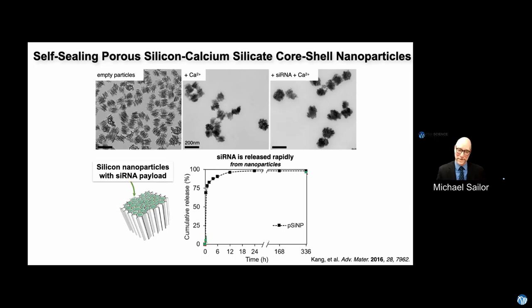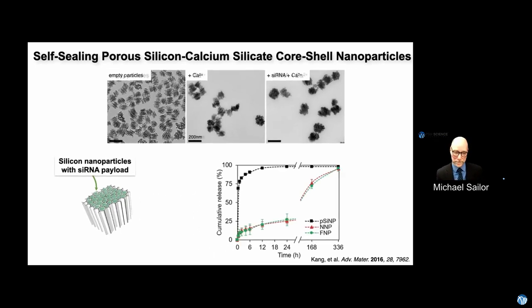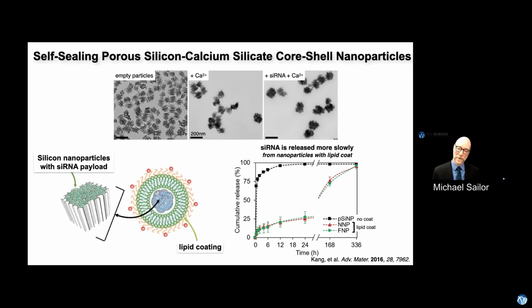But we'd like them to actually stick around for a little while because we want to inject them and have them deliver a drug. And so this was a problem. These things dissolved too fast. So going back to all the lessons we've learned about lipids and how they can stabilize materials, we made solid lipid nanoparticles, where we made the core with our silicon that concentrated the nucleic acid, and then we just wrapped the outside of it with one of those lipids.